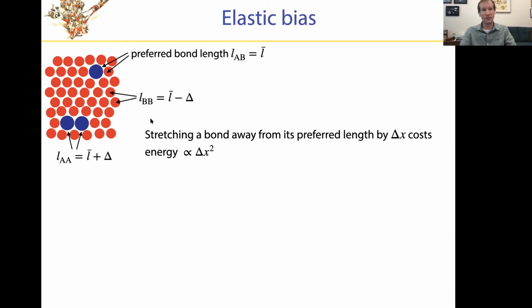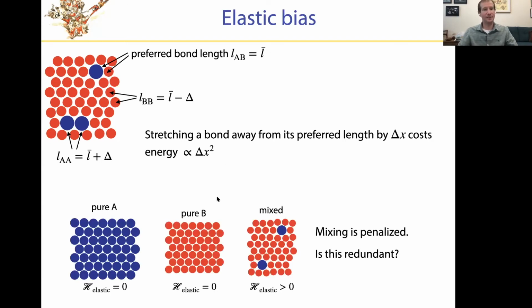So what do I expect from this elastic bias? We said we know precisely what to expect from the local chemical preference by analogy with boiling a liquid. So let's ask here. Well, the lowest elastic energy I could possibly have would be not distorting any of these bonds away from their preferred length. And that's only possible in the pure materials. If I have all A, which is blue, or all B, which is red. In this case, every single pair of neighbors can adopt its preferred bond length, and there's no cost of elastic distortion. Once I start mixing them, I necessarily have to introduce distortions. And so there is an energetic penalty to mixing. And that is the essence of this elastic bias, is penalizing mixing.